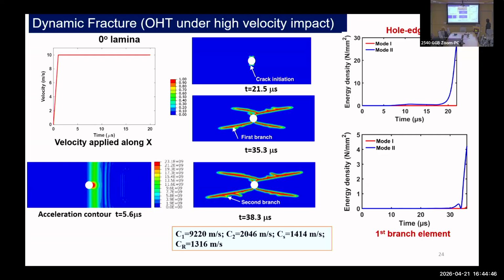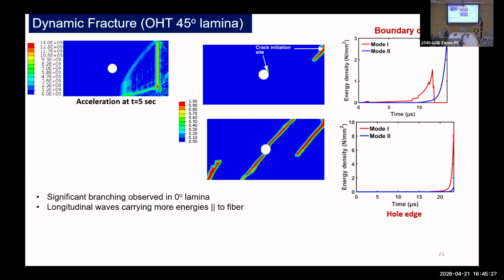If we look at the energy landscape locally, among those 2 modes of energy, which one was the driving force for this case? What we see is that in the crack initiation event, it was purely mode 2 driven energy. You see how high it is? So it was shear driven crack growth, and that's what is happening in the 0 degree lamina, because it's the fiber-matrix delamination that promotes the crack growth. Similarly, if we look at the branching events, we see that it is mode 2 driven too. These are some of the important velocities: longitudinal wave, shear wave, and the Rayleigh wave velocity, which we can use to compare certain quantities such as the propagating crack tip speed, etc.